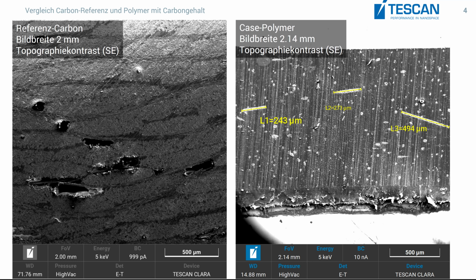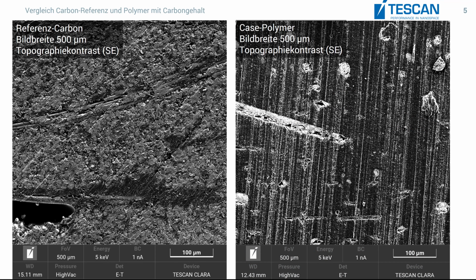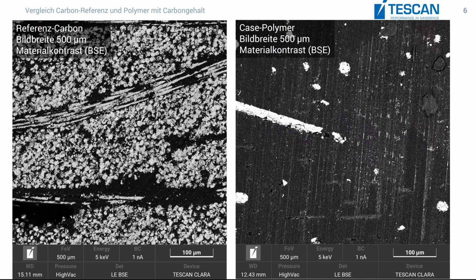If we now switch to a different view, this is much more clear, especially if you compare left to right and pay attention to the white areas, which are the carbons or the carbon fibers. On the left, this is, as expected, about 60% carbon fiber, 60% white material, and about 40% the black material, which could be some kind of matrix material, some kind of glue sticking together the fibers. But now if you look on the right side, there's a lot of black stuff. There's not that much white stuff, which indicates that the amount of carbon fiber is very, very low.